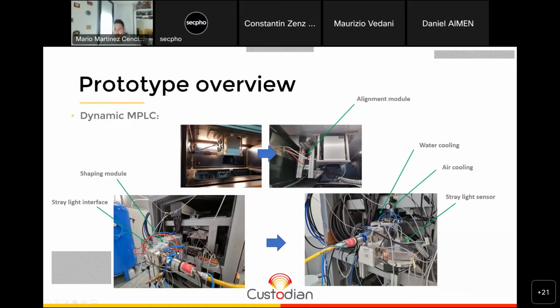Anymore. So this beam shaper is also equipped with a stray light sensor, which is a security measurement introduced by Cailabs, which basically shuts down or triggers the laser when it detects a quick change in the light inside of the beam shaper, right? So here, just to add, some water cooling system was installed in the MPLC to cool down the mirrors, and we also have to include an air overpressure to avoid dust and contamination of the system.